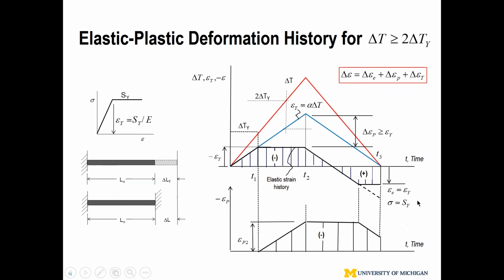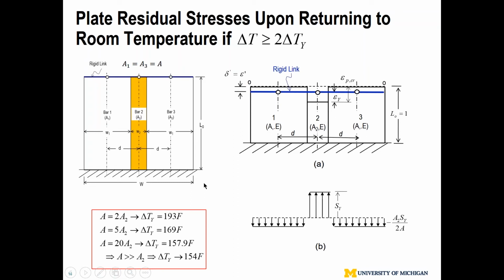That means we're going to continue, say, assuming that's happening, I continue to heat up the material, producing thermal strain, and the thermal strain becomes plastic strain as soon as I exceed delta Ty, but I continue to heat up to peak temperature, and then I go through the same process. This time, what we see is on reverse, the shrinkage is beyond the tensile yield strength of the material, and then I get elastic strain equals epsilon Y, and then I have reversed plastic deformation. So the key message is, as long as this distance equals epsilon Y, or delta T equals 2 times delta Ty, that's a necessary and sufficient condition to develop yield magnitude reduced stress. In that case, the reduced stress will be tensile yield magnitude.